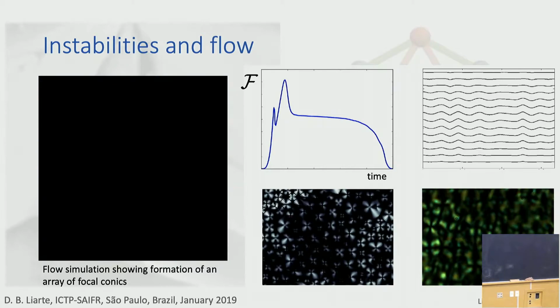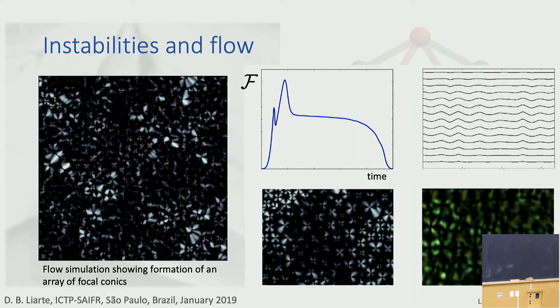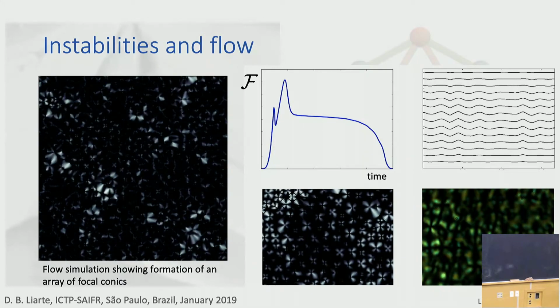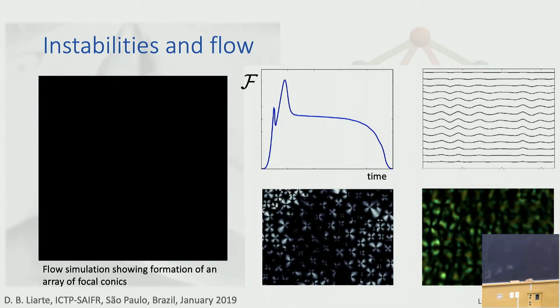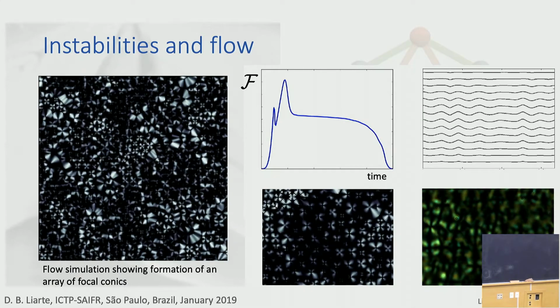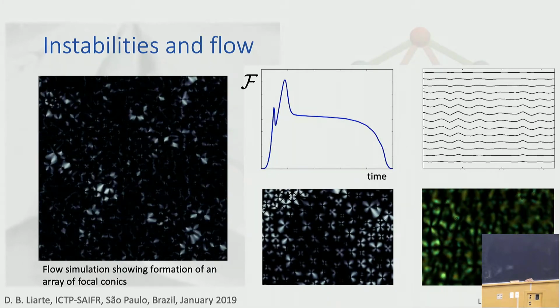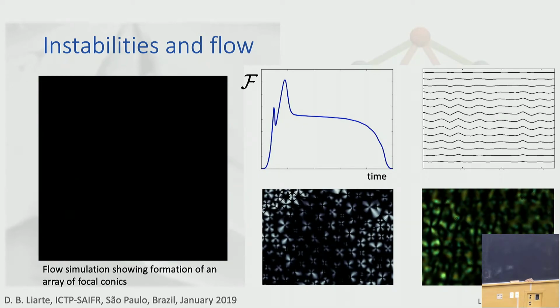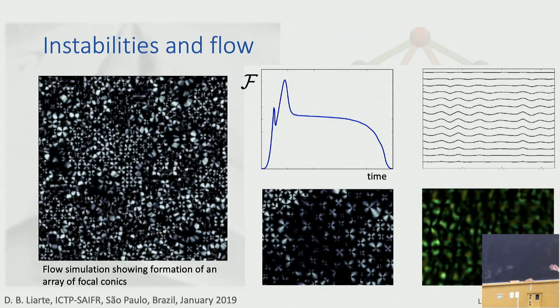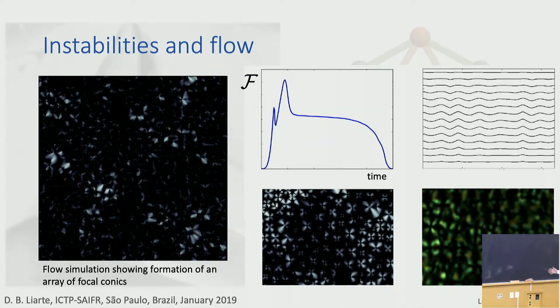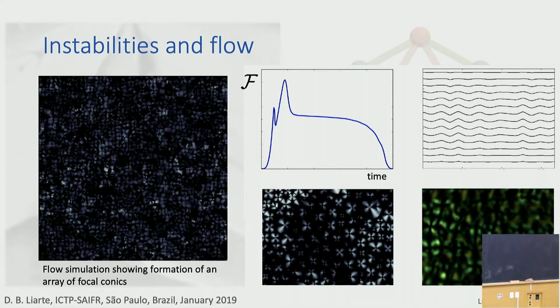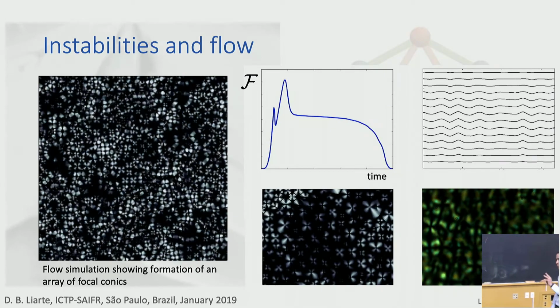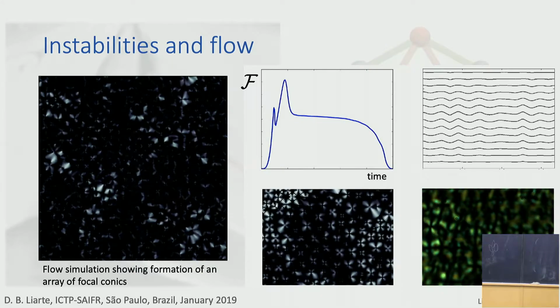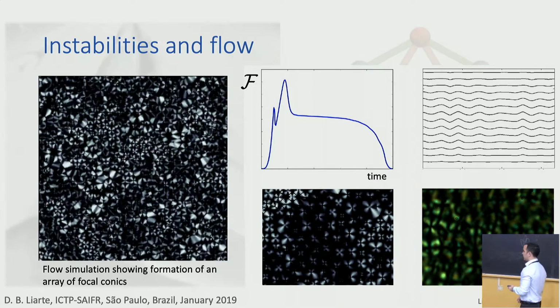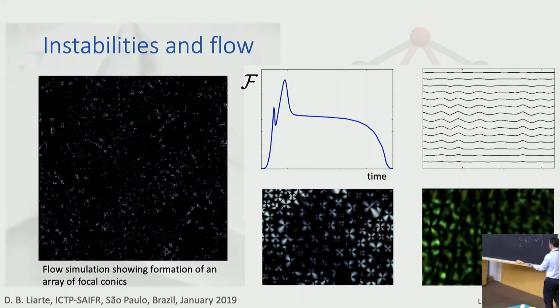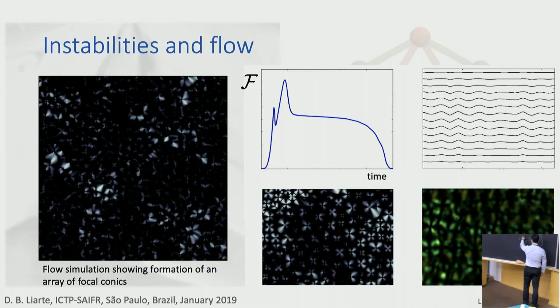That was, it starts with a random initial configuration and evolves in time until the focal conic domains coarsen and grow and evolve towards some equilibrium configuration. And at the end, it just starts back from where it began. So it reached an equilibrium where they had some typical size? I didn't show you that movie. We didn't go all the way towards equilibrium. But if you did, would it have some length scale? Would it be scaling? It would. Yeah, there are two important length scales here. One is the layer spacing, and you can control, for instance, the length scale associated with the layer spacing by controlling the coefficients of these two terms here.